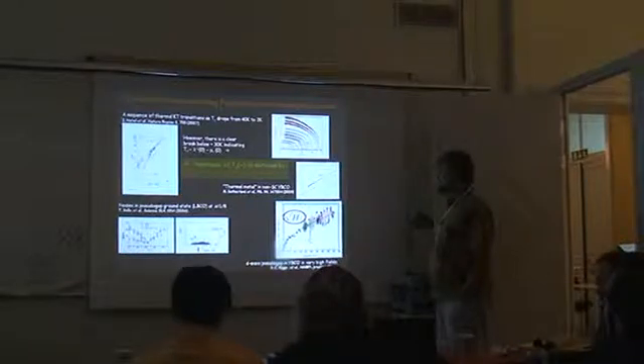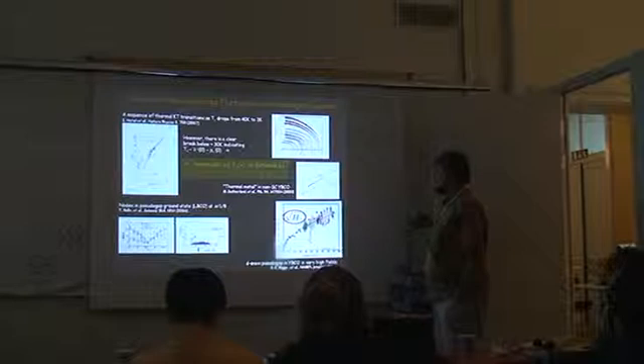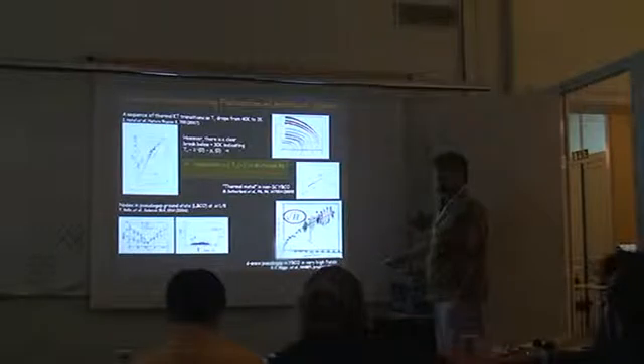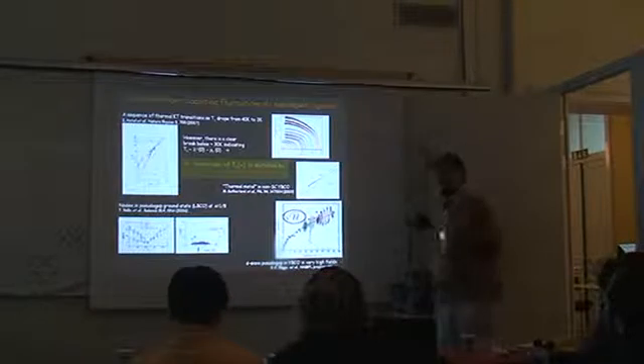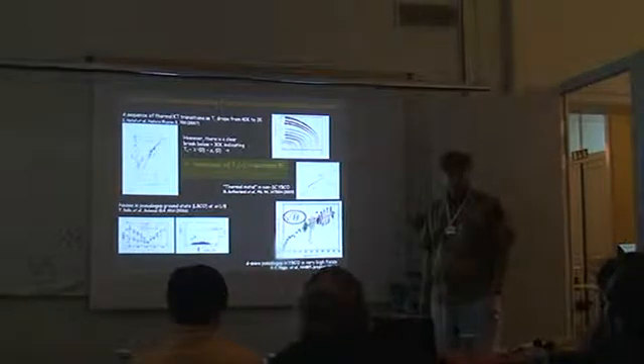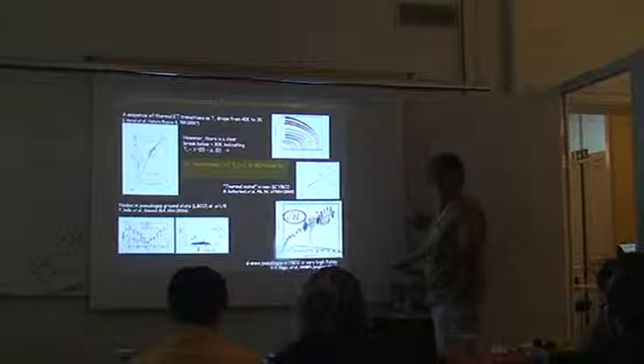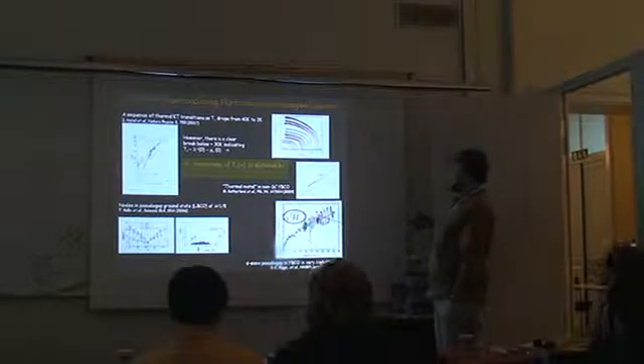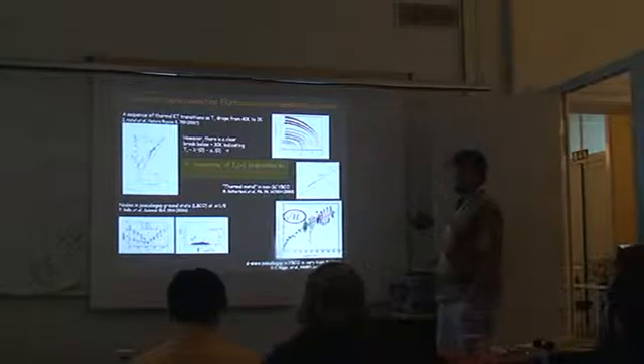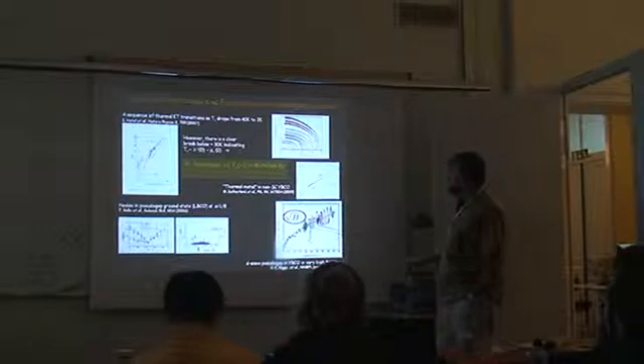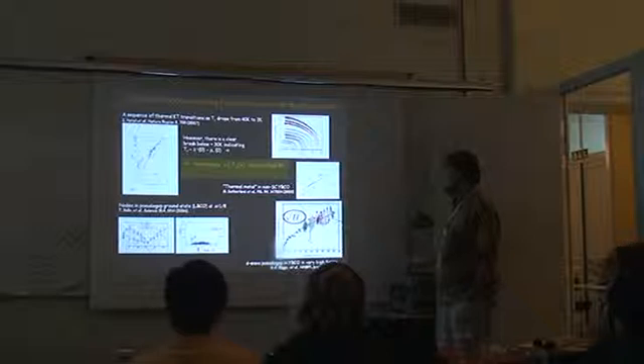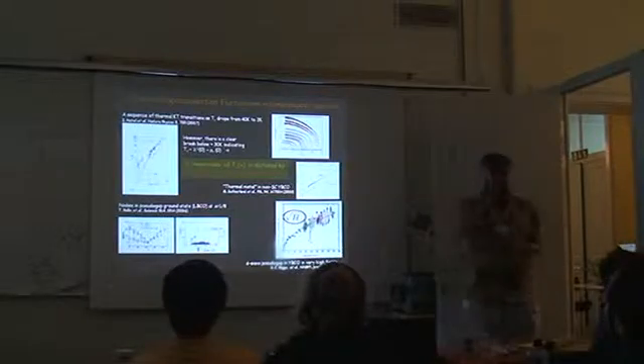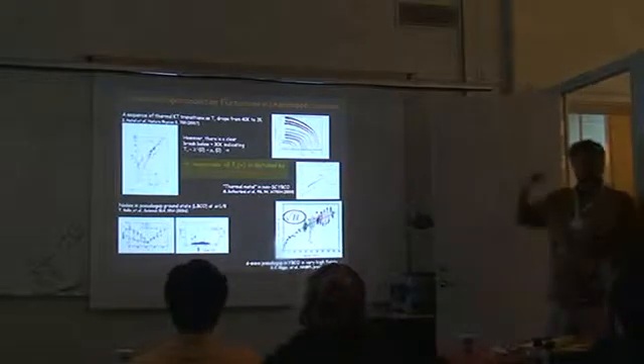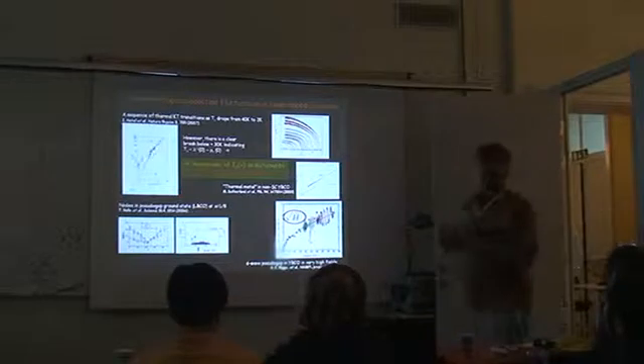I just want to leave you with one thing here that you may find entertaining. Here is the data on specific heat at very low fields. And here you see a square root of H dependence, which is characteristic of nodes in a d-wave superconductor. But that square root of H dependence continues basically the same up to enormous fields, 45 Tesla, long after the superconductor has in fact stopped superconducting.